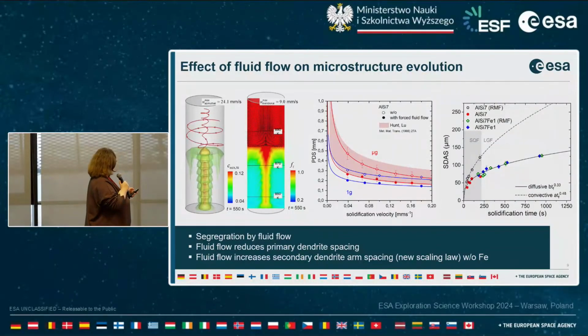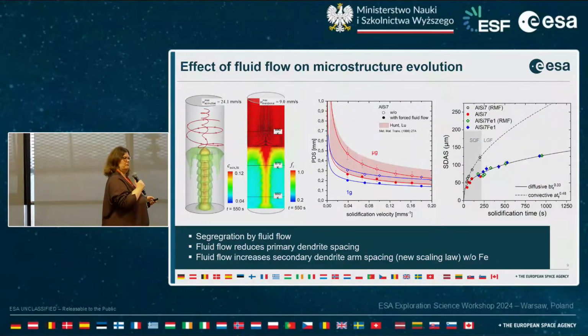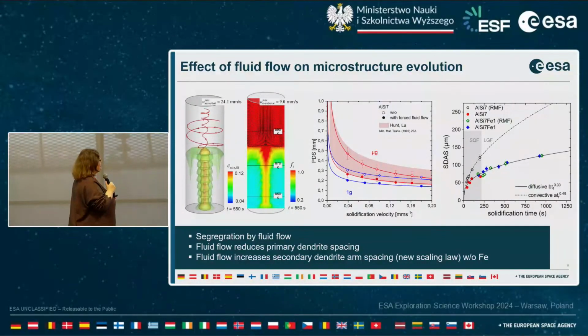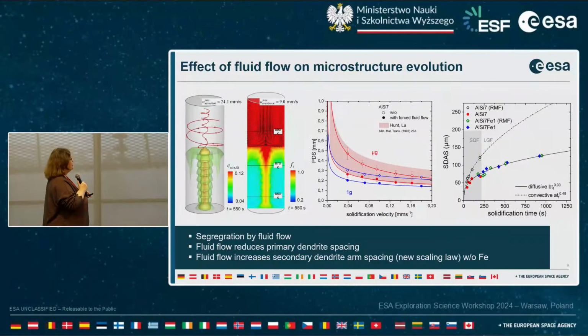Yeah, and so therefore existing theory says that the secondary dendrite arm spacing evolves, or increases, with solidification time. You have more time for coarsening, with a time scaling law with an exponent of 1/3. Okay, checking now what are our results. First here, the red dots coming from experiments under diffusive mass transfer conditions, and they are all lying on this theoretically predicted curve. Great, we said. So we confirmed the theories. Then we switched over to the experimental results on the samples solidified with fluid flow. You think about fluid flow, increased mass transport, coarsening should be faster. So we see not only an increase in the spacings itself, but we found also a new scaling law, a new time dependence with an exponent of around 1/2. Yeah, this is also an important point.